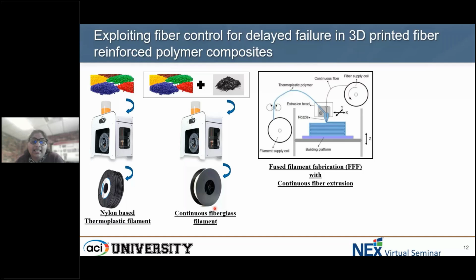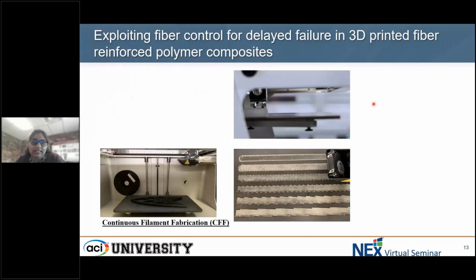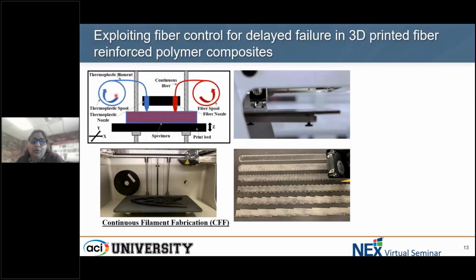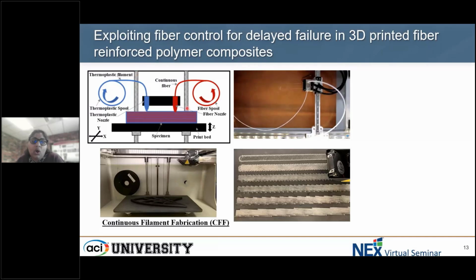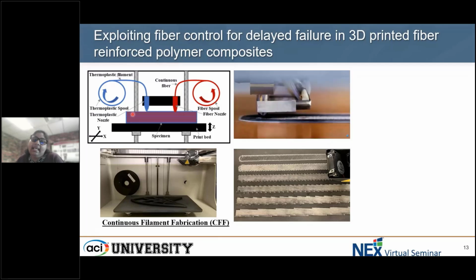And then we use continuous filament fabrication, which in other words is a way to print or extrude a thermoplastic filament along with a continuous fiber in the same layer. So in exactly the same layer made with a thermoplastic filament, you are also able to input a continuous fiber. If you can see this demonstration here, the same layer has both a thermoplastic component and the white colored fiber component. What this technology does is, because of its potential to extrude continuous fiber on the layer, you are able to control with G code which orientation this continuous fiber can take.